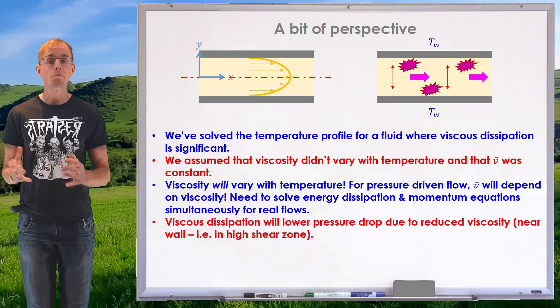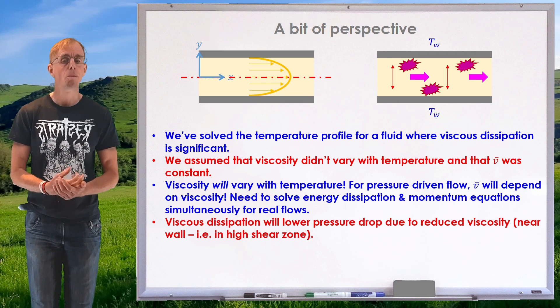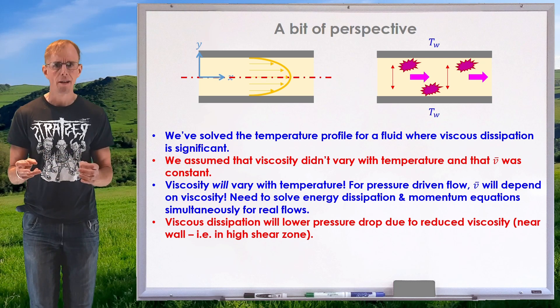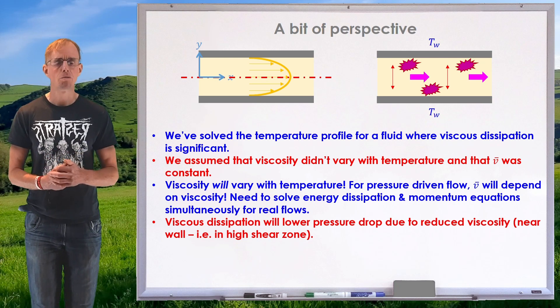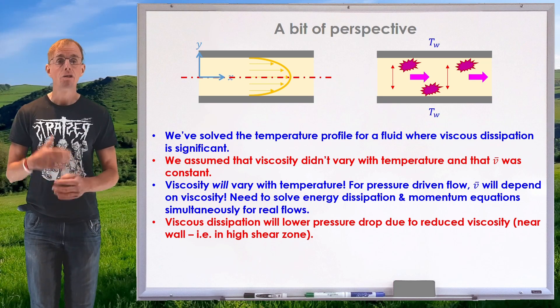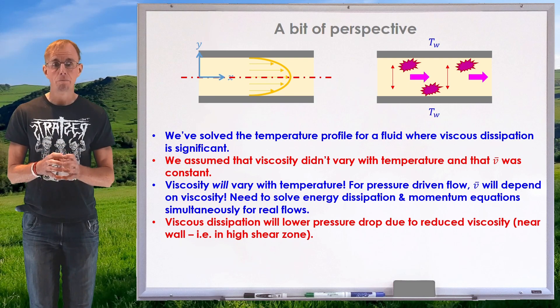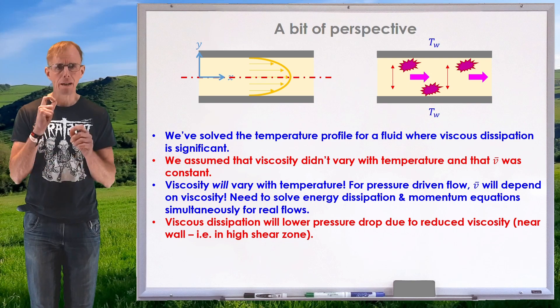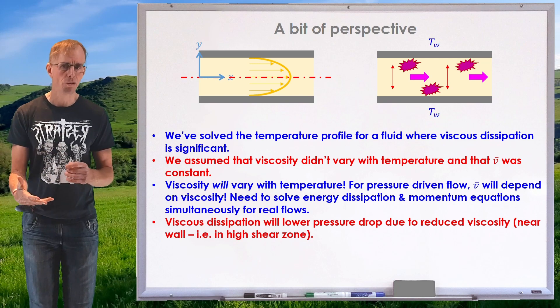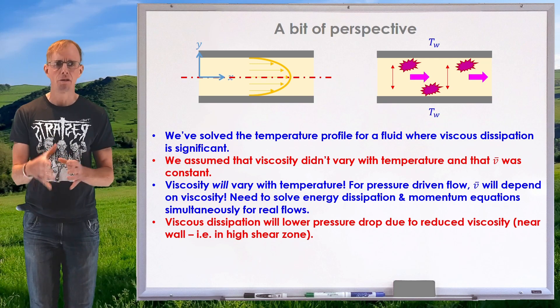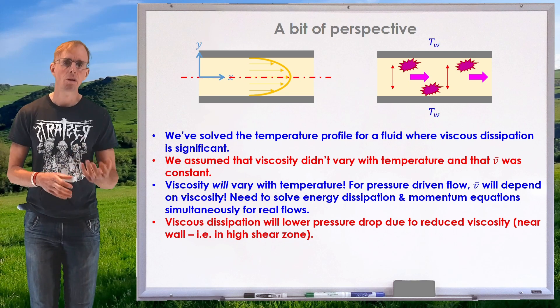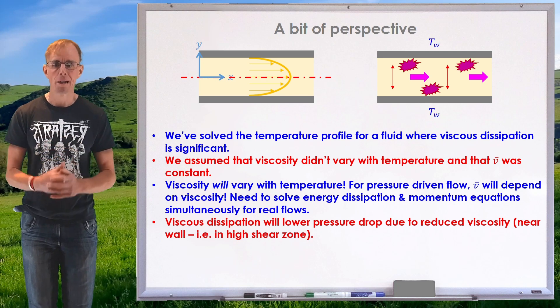The effect of viscous dissipation is to lower pressure drop, so for extrusion operations that might help us to a point. But for precision extrusion through a die with fine features, you'll get high shear zones in those features, a drop in viscosity there, and quite a significant flow imbalance through the die. When designing extrusion dies for profiles containing small features such as lips on sections, we need to think carefully about how much viscous dissipation is happening, what effect that has on polymer viscosity, and whether it will generate a flow imbalance and product distortion.